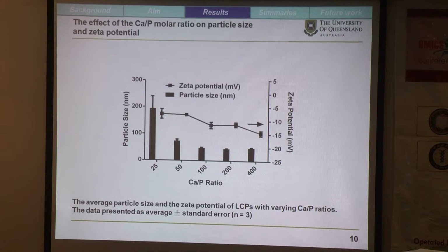Firstly, the particle size and the zeta potential of the LCP nanoparticle prepared at a different calcium to phosphate ratio were tested by dynamic light scattering. As shown in the picture, the particle size decreased with the increase of the calcium to phosphate ratio from 25 to 100, and the size remains unchanged from the ratio of 100 to 400. Meanwhile, the zeta potential decreased slightly with the increase of the calcium to phosphate ratio, which may be related to the relevant amount of the anionic lipid DOPA.